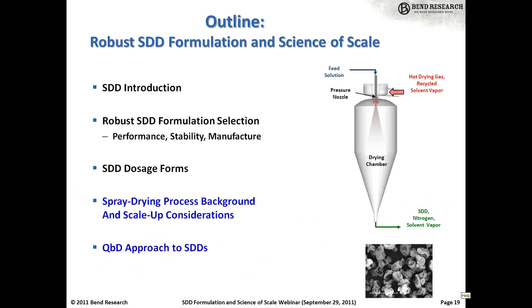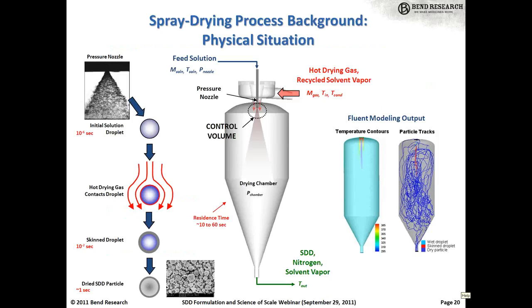Thanks, Corey. And I'll just finish out the talk here by going over a bit of background on the spray drying process, some methodologies for initial process definition, and some considerations for scale-up within a QBD framework. So moving right into some background on the spray drying process. As Corey mentioned, the first step is to prepare a feed solution where you dissolve the API and the polymer in a suitable spray solvent. Some common solvents are acetone, methanol, THF, and blends of those with water, although we have used quite a number of different other solvents as well.